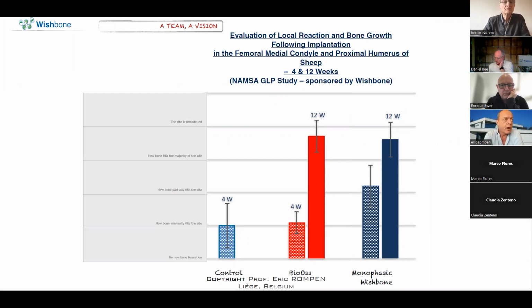In addition to that, we have done many animal studies in big animals, in sheep, in the condyle and proximal humerus of sheep. That has been done independently by the NAMSA group in the US, actually. What we saw is that when we filled some artificial sockets with these materials, we had very impressive results, either with BioOss or with the Wishbone material, at the same level at 12 weeks. But what is extremely interesting is that at 4 weeks, we see a very significant difference. That is, the Wishbone is much more effective at 4 weeks than BioOss.